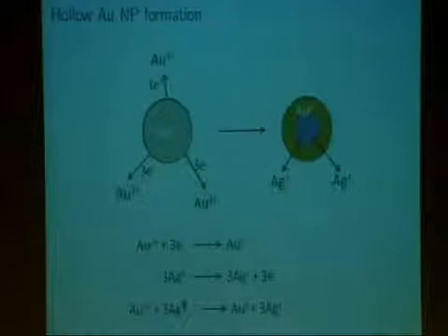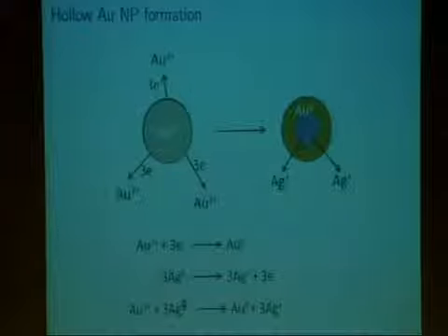And these hollow gold nanospheres can be easily tuned to absorb light at different wavelengths, including the wavelengths in the red or near IR regions. We synthesize gold nanoparticles with a galvanic replacement reaction or a transmetallation reaction. First, we started with solid silver nanospheres, and then we added a solution of chloroauric acid to the silver nanospheres.